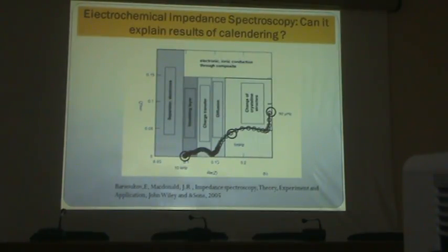This is extensively used in solid oxide fuel cells and other solid electronic devices. So I thought of going this route to figure out how my calendaring is affecting my performance. More or less, if this is your separator, this is your insulating layer, which is absent in the case of NTO. Then you have a charge transfer reaction taking place, Li+ going to Li. Then diffusion through the electrolyte, diffusion through your active material, and finally any change in crystalline structure will be captured in this kind of plot.